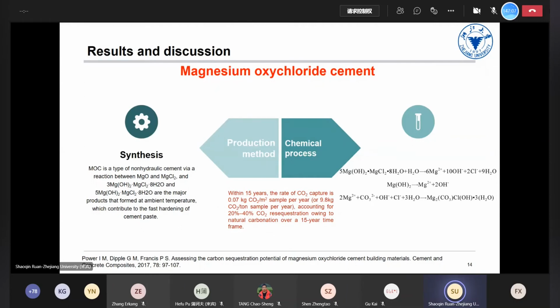And there's a study that, over the past 15 years, examined how carbon dioxide is recaptured into the MOC. It is found that the rate of carbon dioxide capture is about 0.07 kilograms per square meter of sample per year, accounting for 20% to 40% CO2 resequestration owing to the natural carbonation over a 15-year time frame. So this equation is about the carbonation of MOC. When you perform an environmental assessment of MOC, its capture potential of carbon dioxide should also be taken into account, to make it a more comprehensive evaluation.